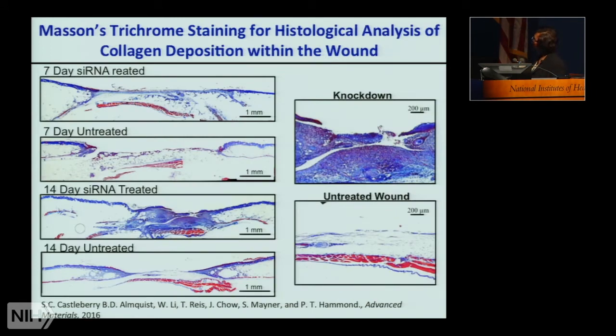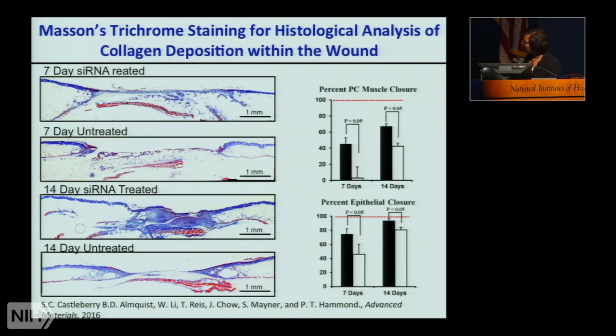If you look at Masson's trichrome staining, we can look at the 7-day and the 14-day treated samples. And here at the top, we have the siRNA treated versus the 7-day untreated. And we also have our 14-day treated and untreated. What you'll see is there's a bridge of collagen, this stained blue sort of ribbon at the top here, that is bridging the wound at 7 days, which we don't see in the untreated samples. And when we get to 14 days, we see that there's a large amount of deposition of collagen present compared to the untreated wound. And here you can see a close-up of that tissue. So there's a stark contrast between the two.